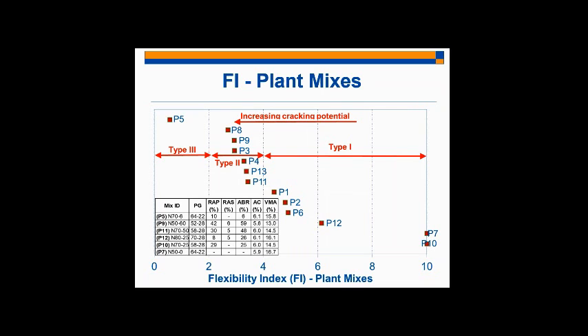As I move further towards the right, I would expect my mixture to be a better performing mixture. And as I move further towards the left, I would expect basically degradation or deterioration in the performance of the mixture. So if we look at some examples, I can see here that P12, so this guy, P12 is again closer to the right side of the spectrum. P12 is a 26% ABR mixture with a 70-28 binder. It's only 8% RAP, 5% RAS.